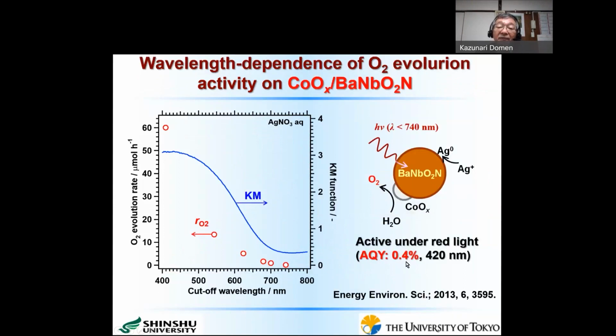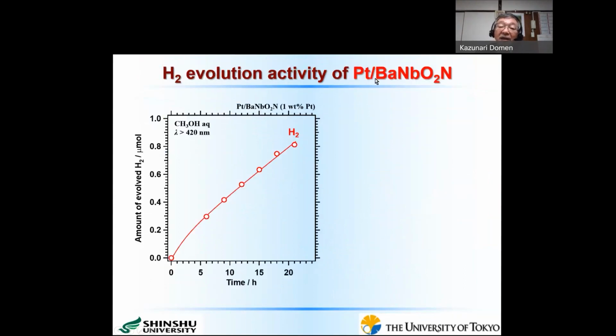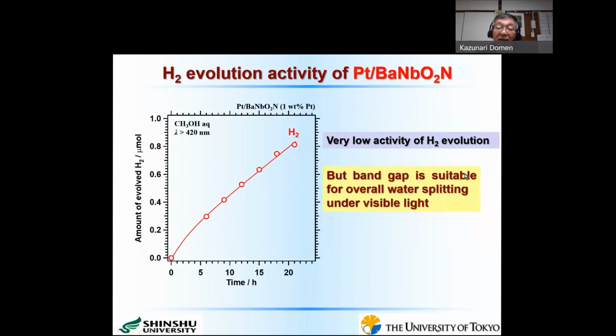Then we also examined the hydrogen evolution activity. In this case, we modified with platinum, but the activity was very low, about 1 micromole. But in any case, this barium niobium oxide nitride was able to produce both hydrogen and oxygen. That means that the band gap of this material is suitable for the overall water splitting reaction under visible light irradiation. So we decided to move to different niobium-based materials.